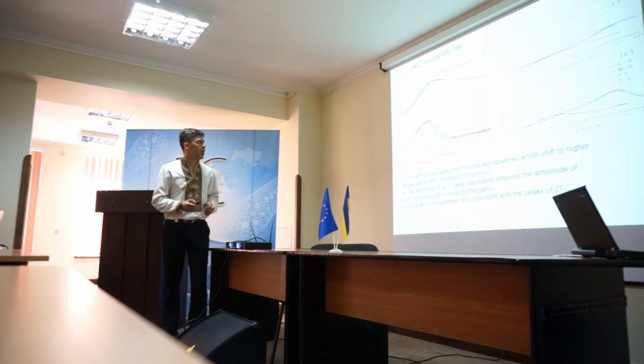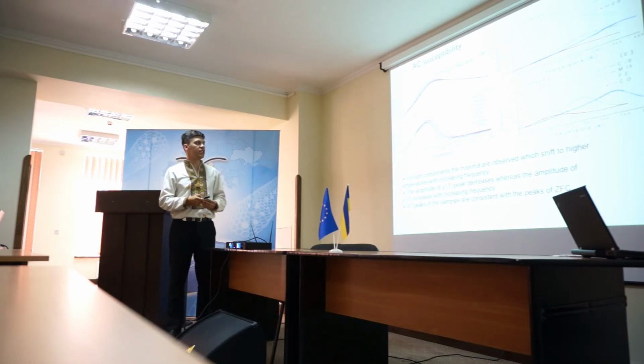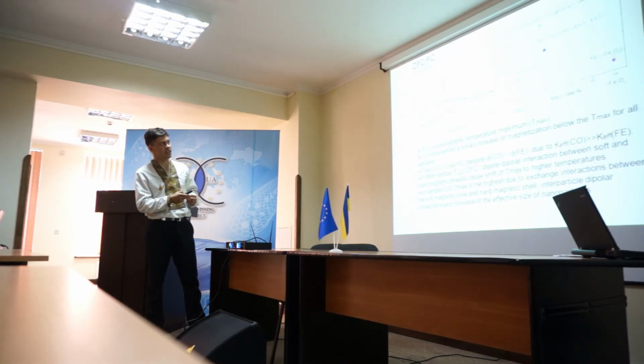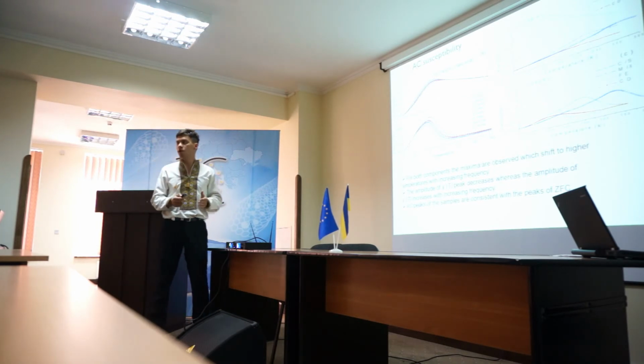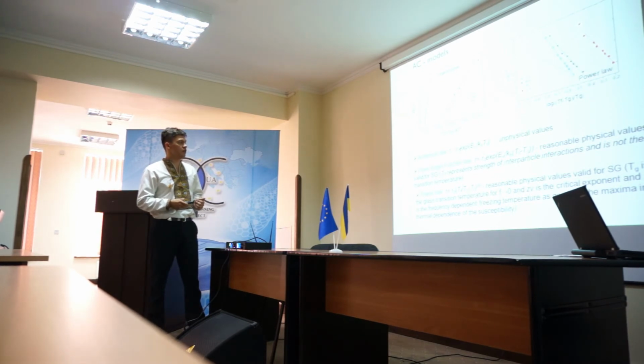To investigate the dynamic properties of the system, AC susceptibility measurements were done. On this picture, we presented the detailed investigation of the magnetic nanoparticles in the frequency range from 45 Hz to 10 kHz. The amplitude of the real peak decreases, whereas the amplitude of the imaginary component increases with increasing frequency. And these pictures present the real and imaginary parts for all samples at 200 Hz. And these AC peaks of the samples are consistent with the peaks of the ZFC curves. And this frequency dependence of the temperature peaks was analyzed using the Arrhenius, Vogel-Fulcher, and power law.